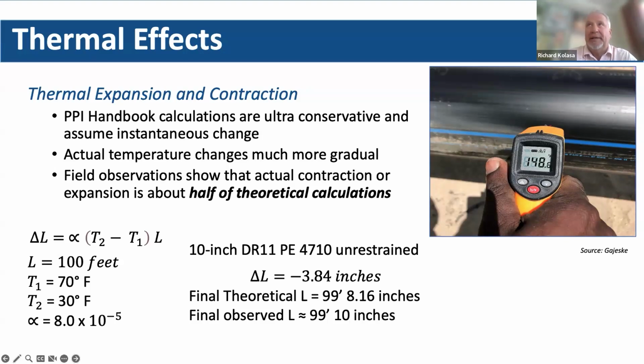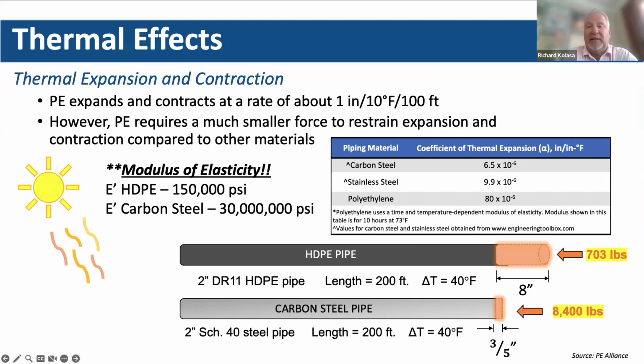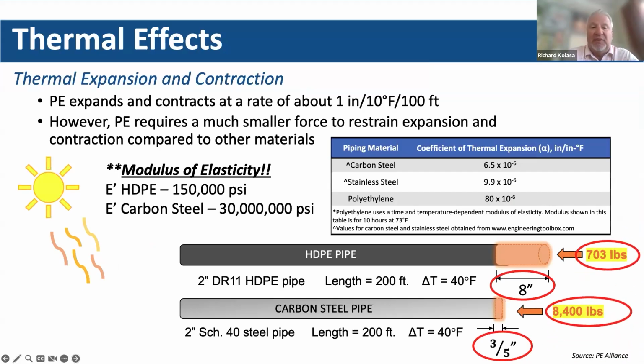We need to be able to manage those expansion and contraction. So this is an example of using the modulus of high density polyethylene of 150,000 psi and carbon steel at 30 million. You can see that the expansion for the carbon steel is very, very small, and yet the high density is very, very large comparatively speaking.